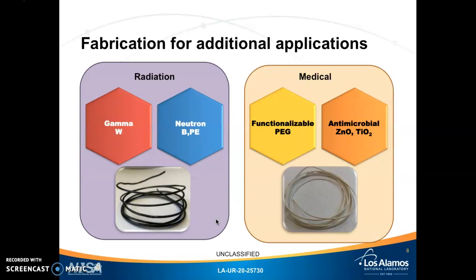Once we were able to successfully make radiation shielding filaments, we designed filaments for other applications. For more radiation-based composites, tungsten was used instead of bismuth, and for shielding neutrons, filaments with polyethylene and boron were used. For medically based composites, the biocompatible polyethylene glycol was incorporated along with the antimicrobial ceramics zinc oxide and titanium dioxide into a PLA polymer network.